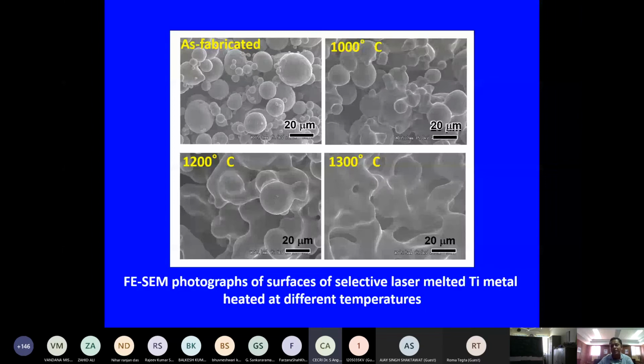And you can see this is a scanning electron microscope image after the 3D printed components are done. There are so many loosely bonded particles adhering to the walls of the as-fabricated component. When we heated the component above 1000 degrees in an inert atmosphere, you can see sintering or bonding of these loosely bonded particles has happened, and it has formed necks. The necks started forming around 1000 degrees, and above 1200 or 1300 degrees you can see they have formed nicely, creating so many micro pockets on the inside as well as the outer surface of the 3D printed component.